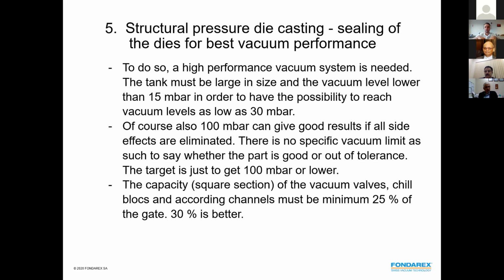So we have to concentrate on the whole concept and on the parameters, and not only on the lowest possible vacuum result. On the other hand, if somebody is investing into a new cell, which is designed for structural part castings, of course, we have to buy the equipment which can guarantee 30 millibar if ever we need it. Sometimes we need it. It's not possible to get a perfect part without getting very low. But in most cases, we already get good parts with 100. So this is just to evaluate what we should buy. We are not buying it because we need 30 millibar all over the place, but we should have the possibility to get 30 millibar.